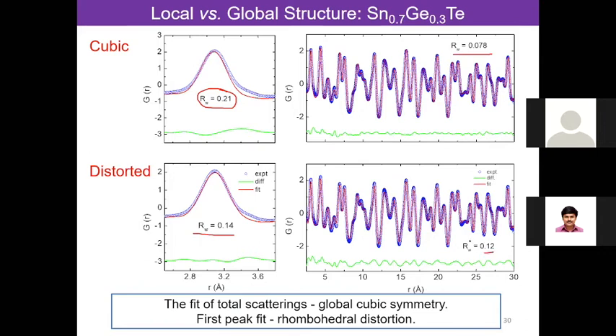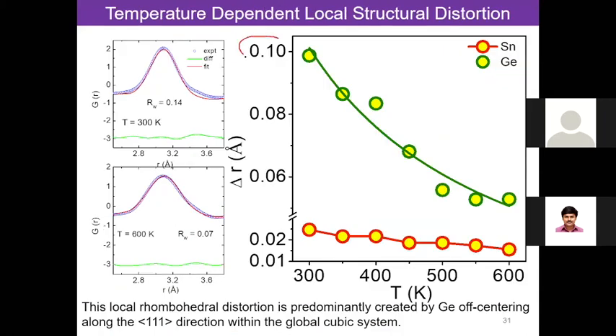But that means we have this scenario. Local structure, the germanium is distorted, but global structure, this germanium distortion is less. So it averages out and this gives rise to centrosymmetric structure. So locally, this germanium distortion is actually coming from the germanium lone pair, as I told you, and that we showed by NMR experiment. And this off-centering of germanium is only 0.1 angstrom.